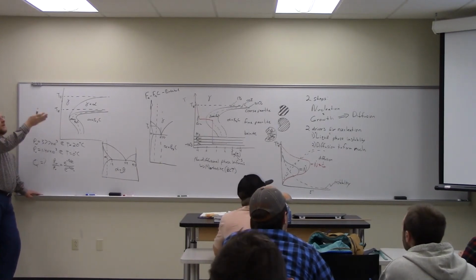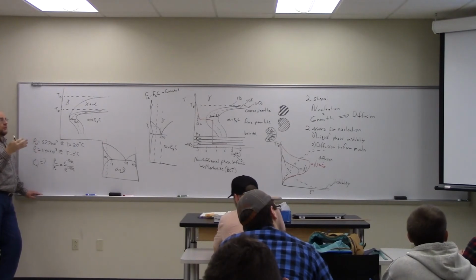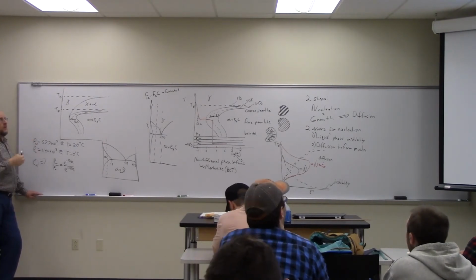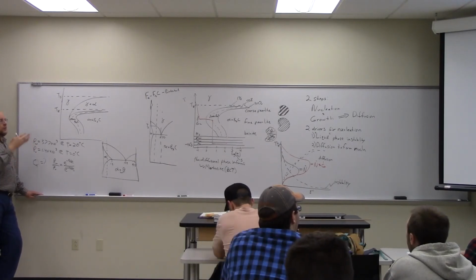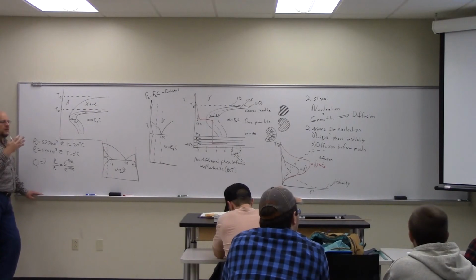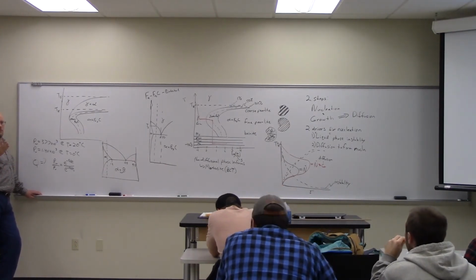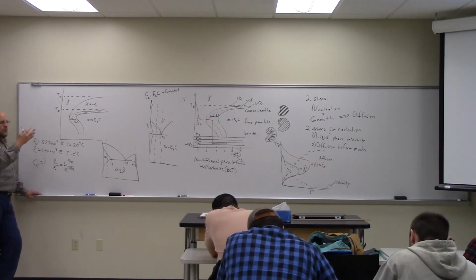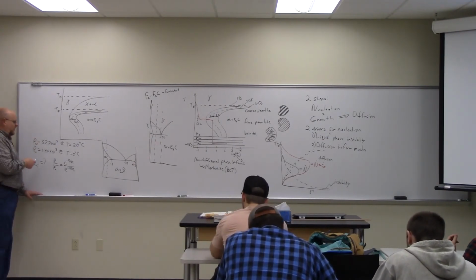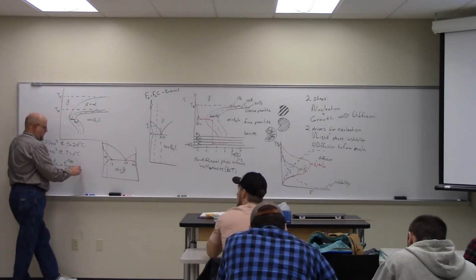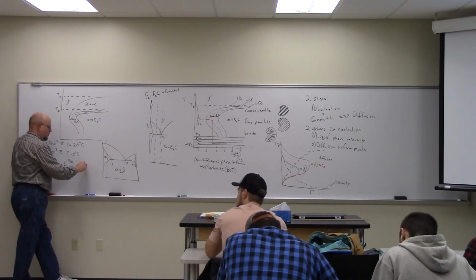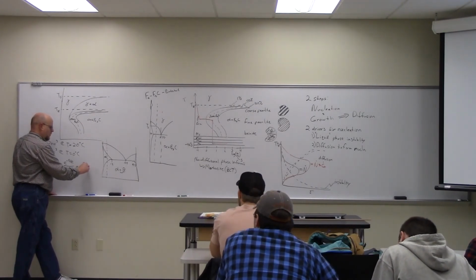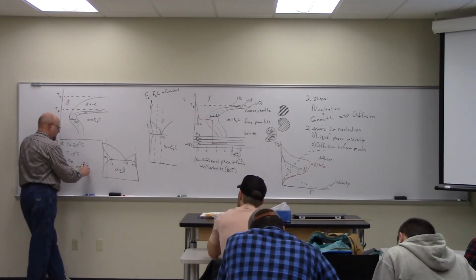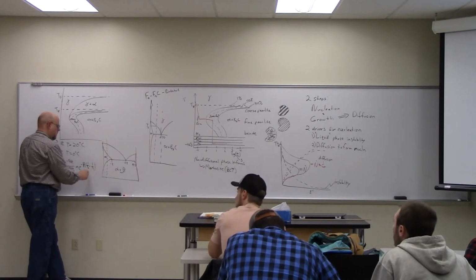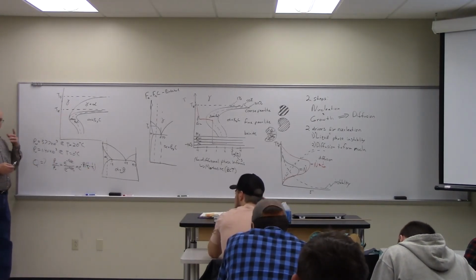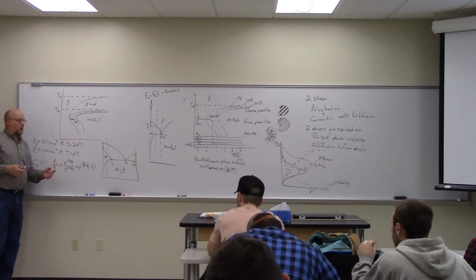That's the equation. It says, although section 10.1 concentrates on crystal nucleation and growth, so that's a growth rate, similar kinetics laws apply to solid state transformations. So growth rate and precipitation rate have similar functions. Basically they're saying they're both Arrhenius behaviors. That makes sense. Both precipitation and growth are Arrhenius behaviors. So we can take the ratio of those two. So that's e to the minus Q over R times 1 over T2 minus 1 over T1. So we get rid of the C and we can solve for Q because we know R and T.